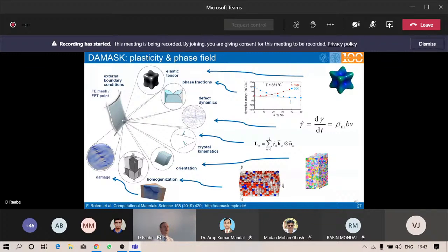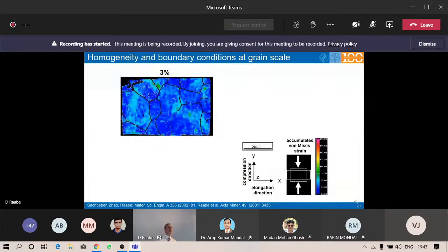I'll show you here a 20 years old example on which we worked in the beginning. A high purity aluminum grain, you see in black the grain boundaries. So a very simple example with columnar grains, and that was deformed like shown in this little animation. That was deformed by a lubricated channel die experiment in order to achieve near plane strain boundary conditions, so to have well-defined mechanical constraints.